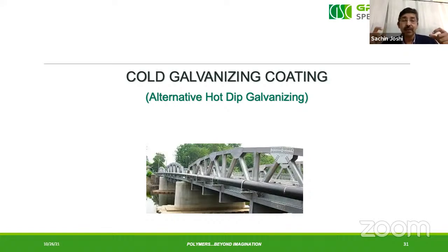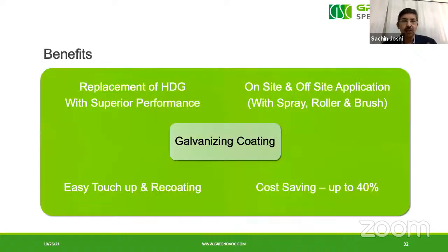You have to dip the structures into molten zinc at high temperature, with tin and nickel. Toxic fumes, not good for the environment, not good for humans. So we have developed a coating which replaces hot dip galvanizing with superior performance. It is tested at Exova, Singapore for ASTM A123. All properties are tested as per galvanizing properties. It is 30% better than hot dip galvanizing.